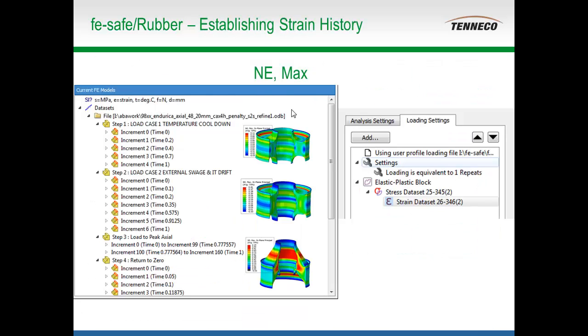So the FE-safe rubber code is certainly able to take into account elevated temperature, time at temperature, so aging effects. Ozone, since most of the compounds are formulated to be ozone resistant, unless you were dealing with the type of part, say, a bridge bearing pad that's got a 50 or 100-year life, where you need to pay attention even more accurately to the effects of really long-term ozone.